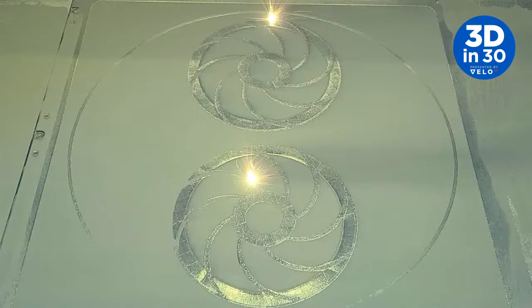The first starting point is having a good powder bed and making sure that's nice, uniform, and even. But a lot of where the quality issues come from, one way or the other, come back to the optical path. We're basically using high-powered lasers that are then being redirected into the processing chamber, and those lasers are melting the powder into a liquid melt pool, which is then adhering to the part below it. And there's a lot of critical aspects that you need to control there: the laser power, the spot size of the laser, and then one of the big things which we're going to talk about today is gas flow and how to handle the welding byproducts.